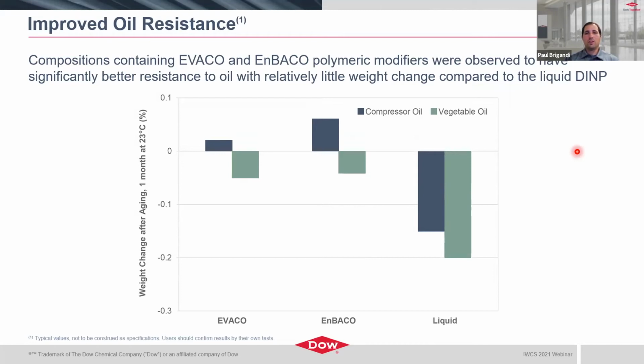And in both cases, what you're looking for is zero change here in weight after aging for a month in the particular liquid or oil. And you can see that the change with the polymeric plasticizers is quite low, particularly compared to that of the liquid. Again, showing that the migration is minimized and it is compatible and miscible within the PVC, whereas the liquid would tend to migrate out. And so this again is going to be important for those applications requiring some different fluid resistance and maintaining those properties over time.